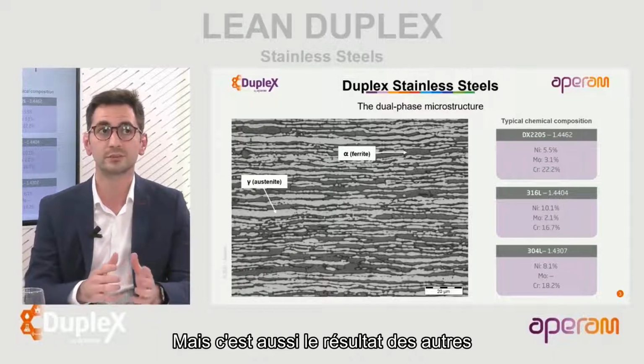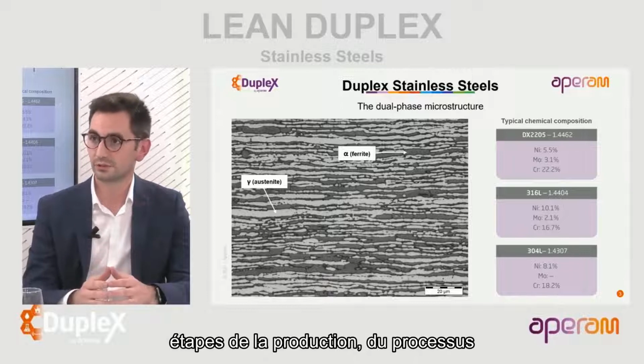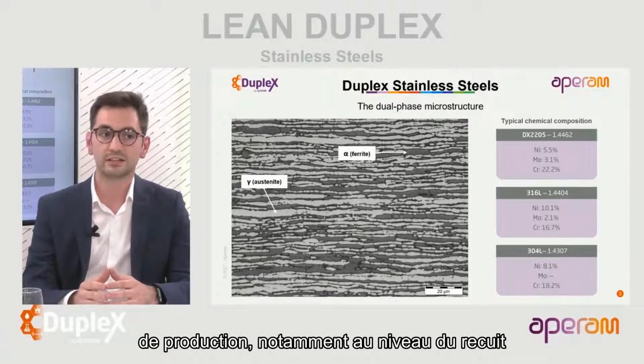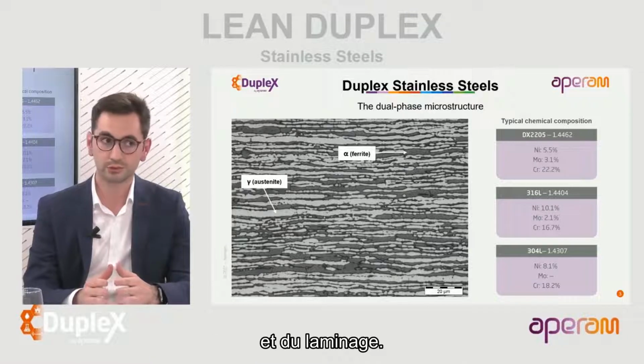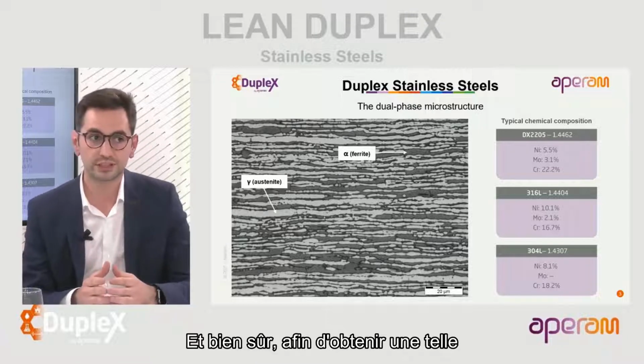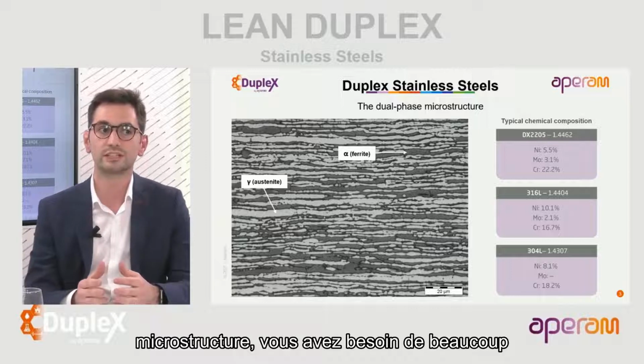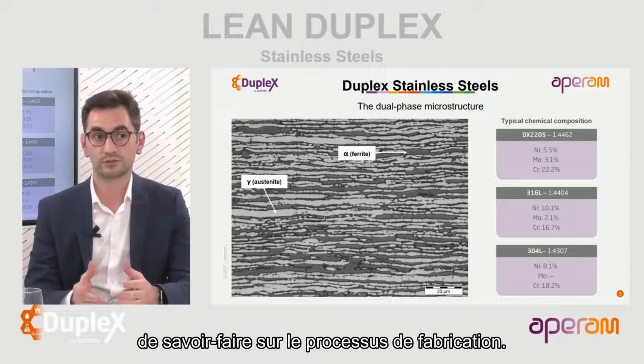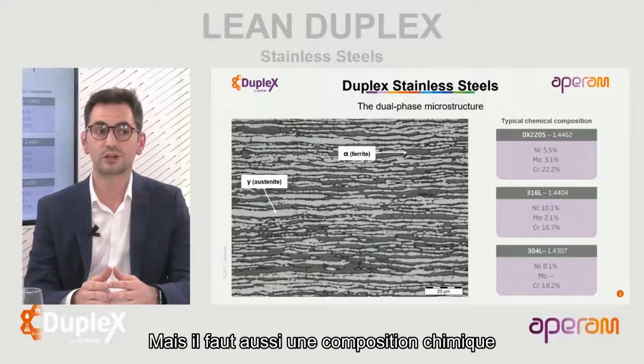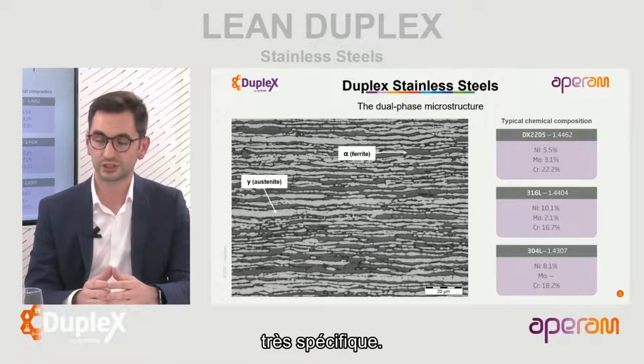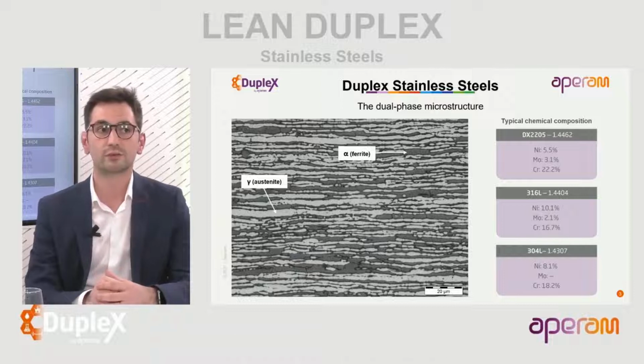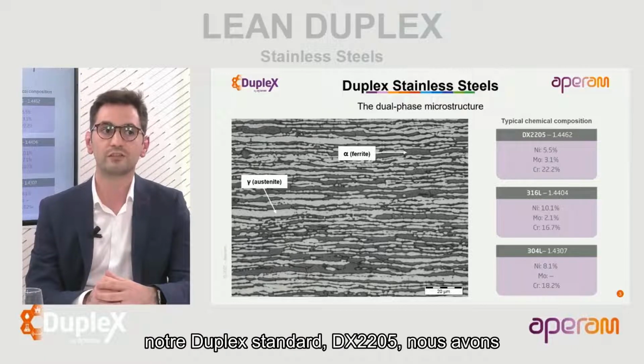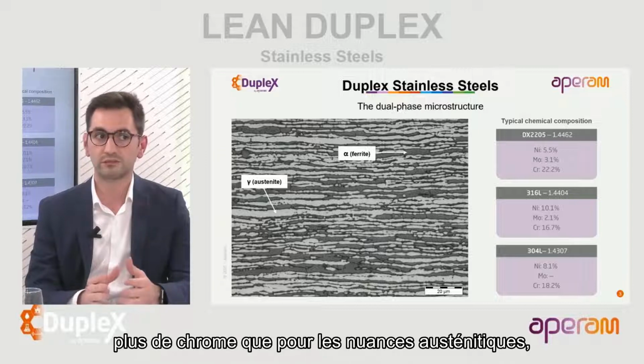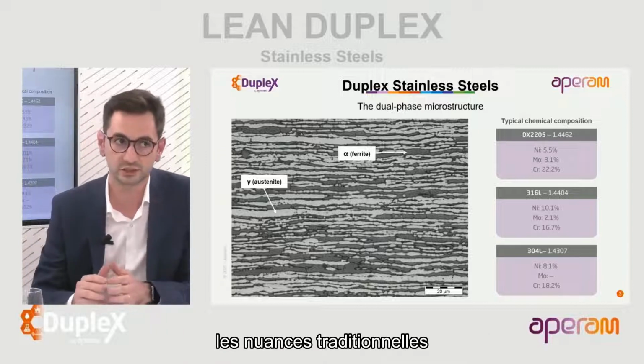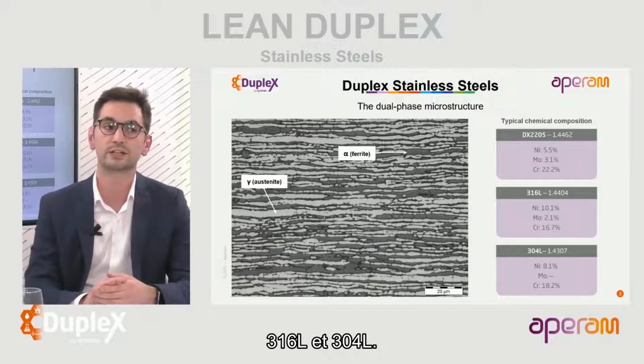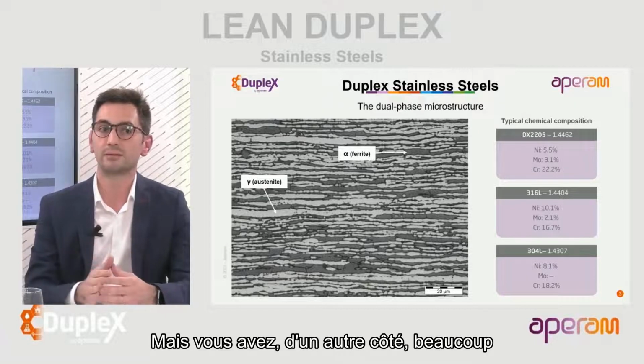But it is also the result of the other steps of the production, the manufacturing process, especially the annealing and the rolling processes. And of course, in order to obtain such a microstructure, you need a lot of know-how about the manufacturing process, but you also need a very specific chemical composition. We can see here on the right that for our standard duplex DX2205, we have more chromium than for the austenitic grades, the traditional austenitic grades 316L and 304L, but on the other hand, much less nickel.